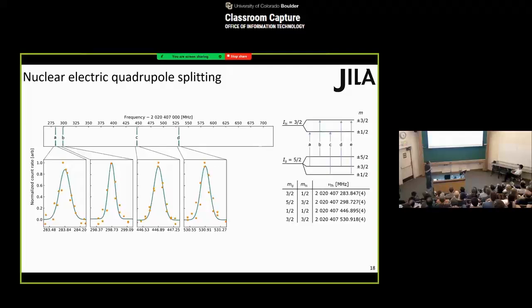Nevertheless, we can determine the absolute transition frequencies of these 4 lines, and then we can predict where line E should be. So if we go back with our experiment and actually check where line E is expected to be, indeed we see some spectroscopy features there, and its transition frequency matches very well, within the uncertainty region of where we expect it to be.